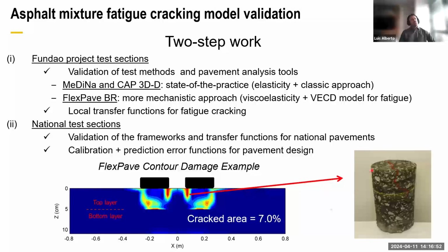This is happening in the field. When we extract the cores and analyze, we have the upper layer totally damaged and the bottom layer is new, no damage. So this kind of analysis was made for many different test sessions to identify where the damage was and if they were really damaged. And this was the first point, a kind of validation. And then the next step: we are confident that our framework, what is the framework? Lab testing, pavement analysis, computational analysis, and the results, we got confident that they make very nice predictions here.